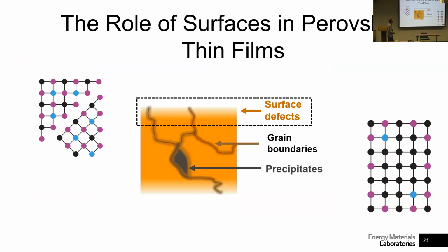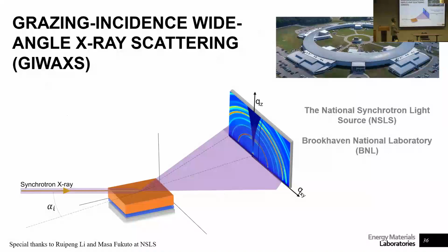Okay, moving on to surface defects. That's something that we also do at a synchrotron. We are interested in looking at surface chemistries, which we actually do here with XPS at Georgia Tech. But we also do X-ray scattering at very, very low angles, and that allows us to look at surface defects in structure. We do that at the National Synchrotron Light Source at Brookhaven National Lab, where we have a very powerful X-ray that has a specific angle. When that X-ray hits our sample, there's some scattering.